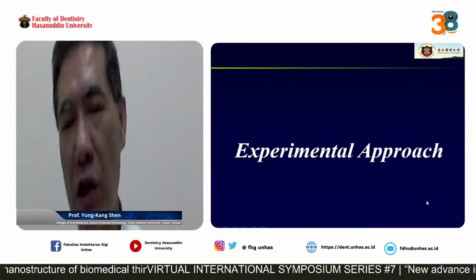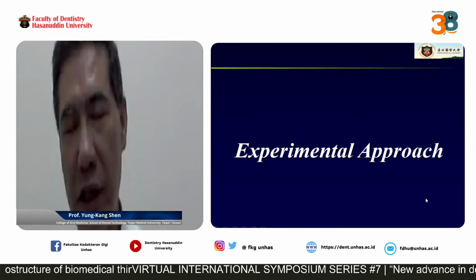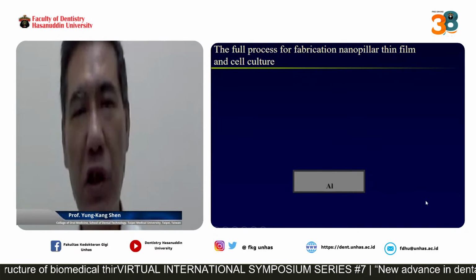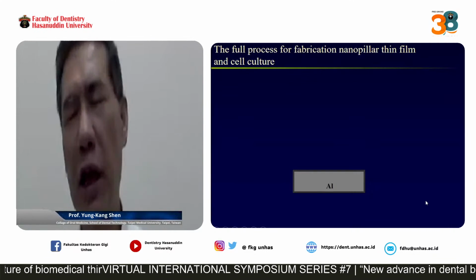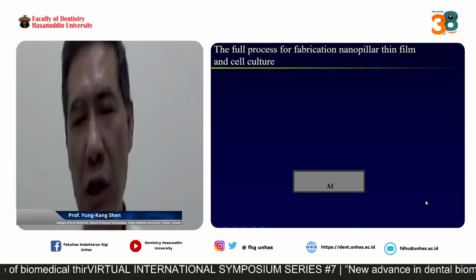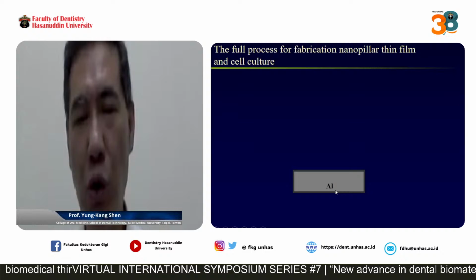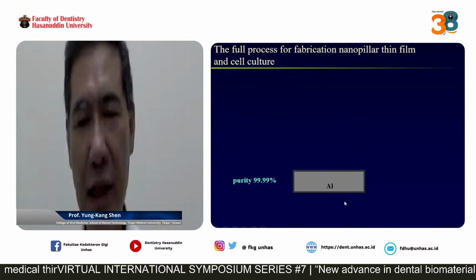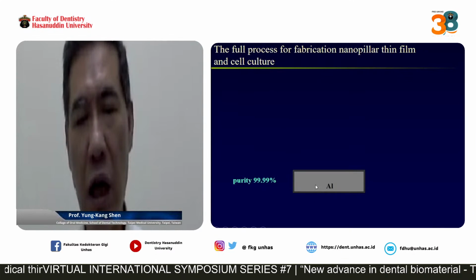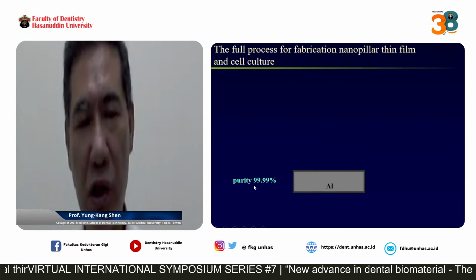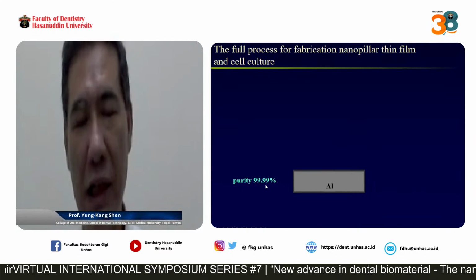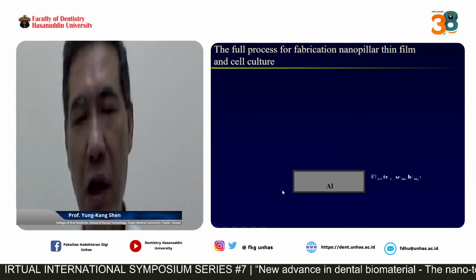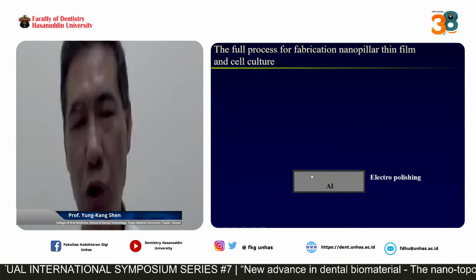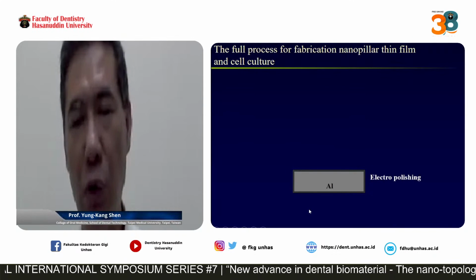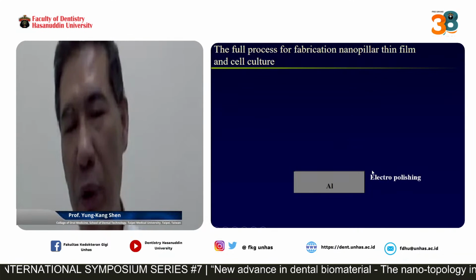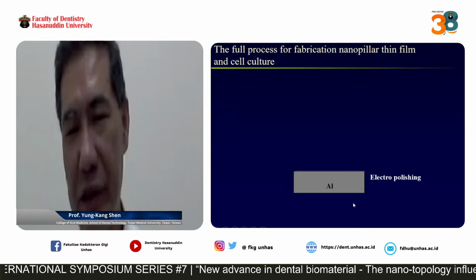Now I will talk about the experimental approach of this research. First, how we make the nanopillars and do the cell culture. First, we buy the aluminum tablet from the company. Our aluminum component has a purity of about 99.99%. Then we use electropolishing to polish the surface of the aluminum tablet, so we can get a very smooth aluminum tablet here.